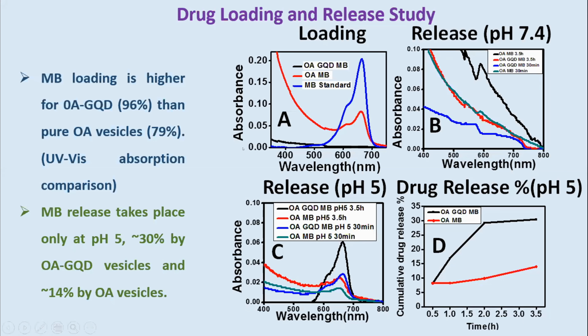But there's an advantage of this vesicle, because it can mimic our cell membrane. That's why this vesicle system is very important. So my composite system released around 33 to 34%, but pure vesicles released only 14%. So our nanocomposite is very efficient in pH dependent drug release. And finally, I found that incorporating carbon-based nanoparticles into the vesicles enhances their efficiency or their functions. So I thought that if we see other applications with similar composite systems, then I think we can get better results.